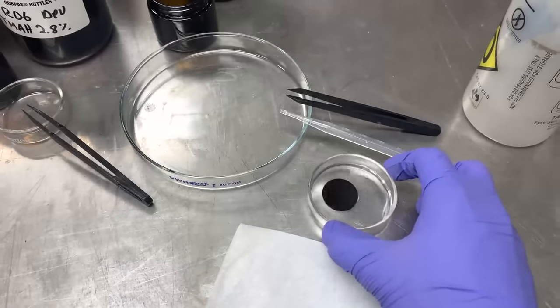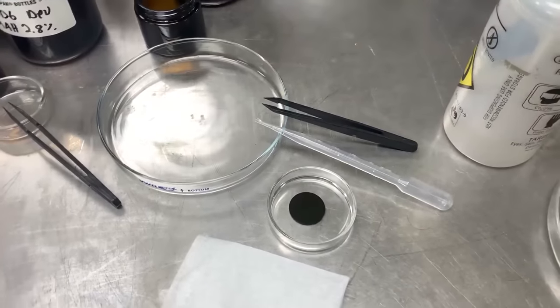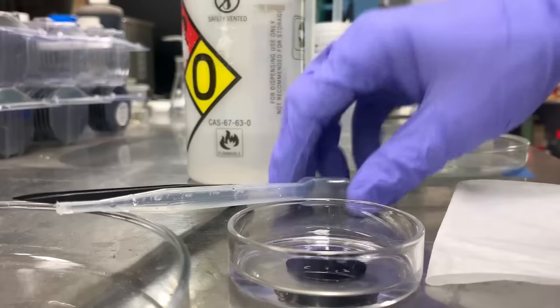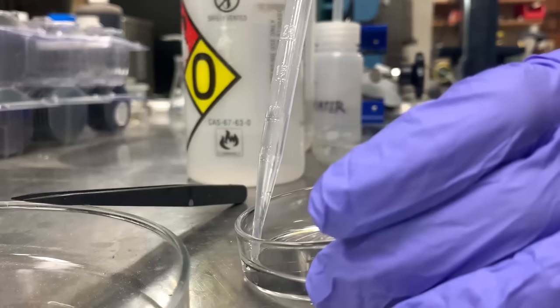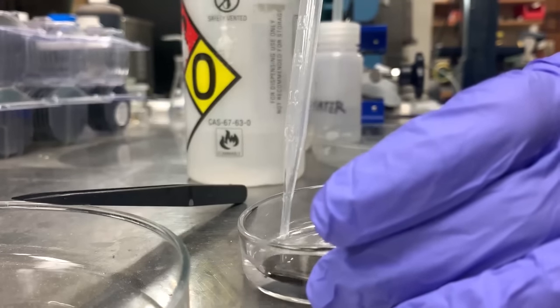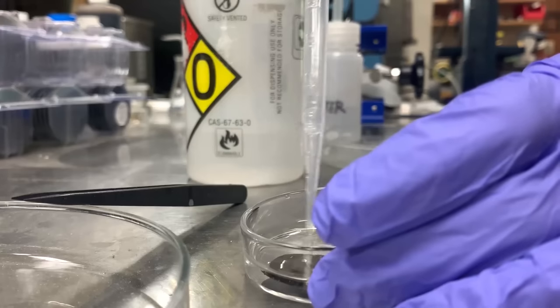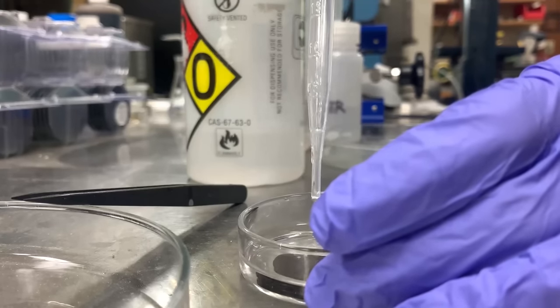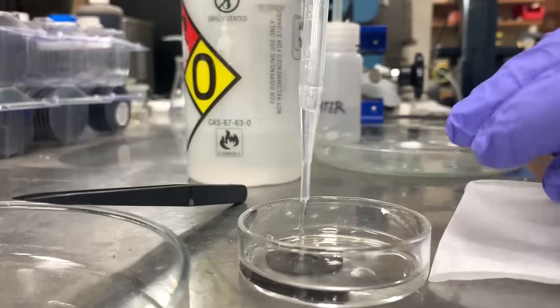If you're using a negative photoresist, that is, the exposed parts become less soluble in the developer and stay behind, then a post-exposure bake is required, just an extra step in there, but we don't have to do that. So we go right over to develop in a couple percent potassium hydroxide solution for about 40 seconds. After the wafer's developed, we can stick it in the microscope and see how it worked.